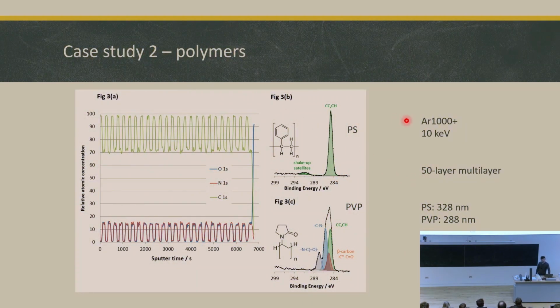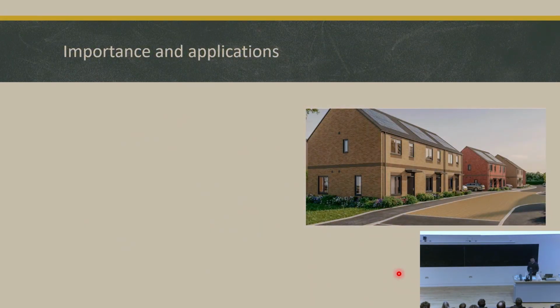In this polymer study, we use this second type of etching method to etch polystyrene and PVP. They are multilayers, 50 layers stacked on each other. We can see that polystyrene only has carbon in it, but PVP has carbon, nitrogen, and oxygen. So we can see the oscillation of those element concentrations as it reaches either the PS layer or the PVP layer. They are both important materials for plastics manufacturing or water-soluble materials. So XPS, of course, is important in materials as well.